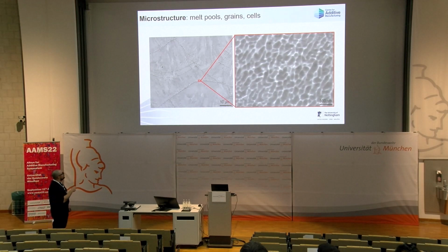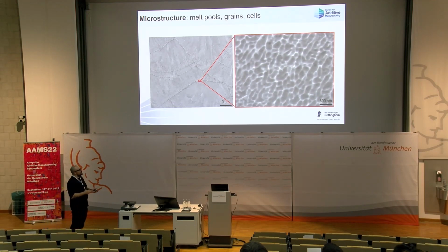And then when we look at the melt pool boundaries here, it's a bit easier to see cells with a FEG SEM, for example. What we see here again is this very small cell size, which is thought to be the main reason for the strengthening of this alloy.